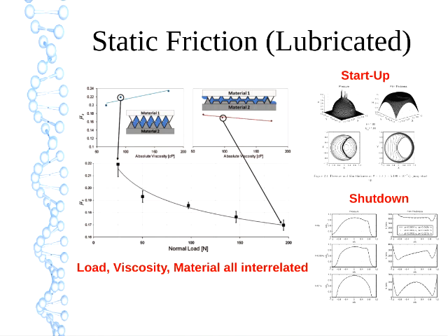We'll look at the bottom of those three graphs. We're looking at the normal load. As you increase the normal load, the static friction goes down. So with the coefficient of friction, it's generally assumed to be constant with respect to normal force. Here we're seeing that is not the case at all.